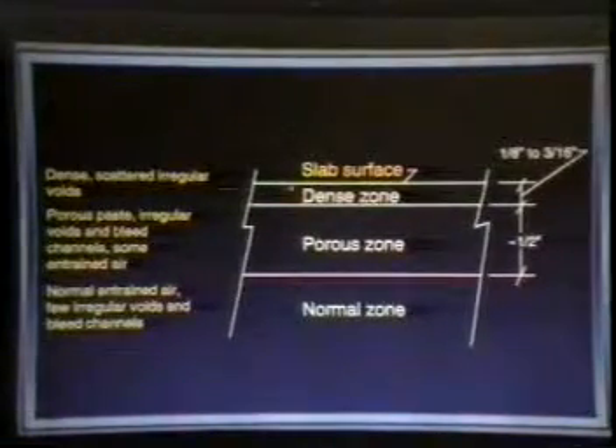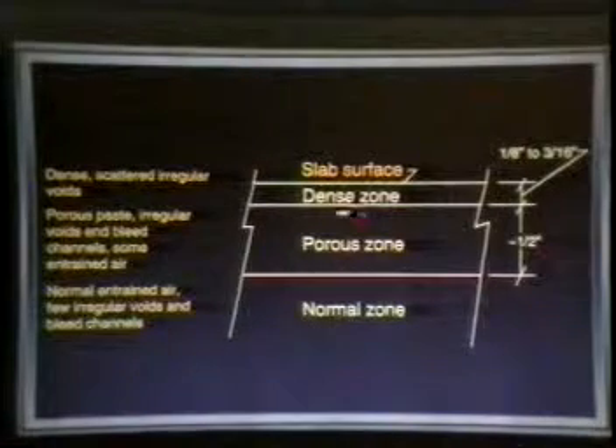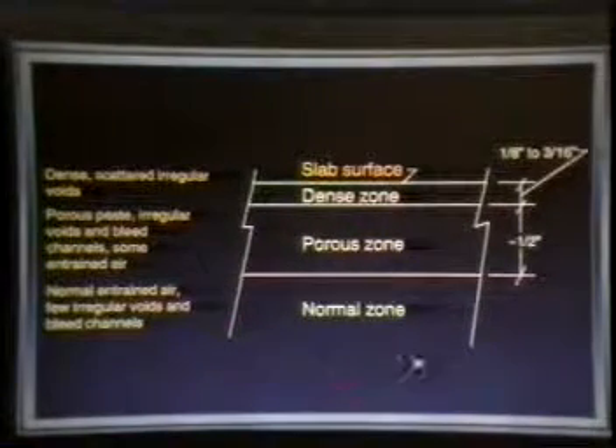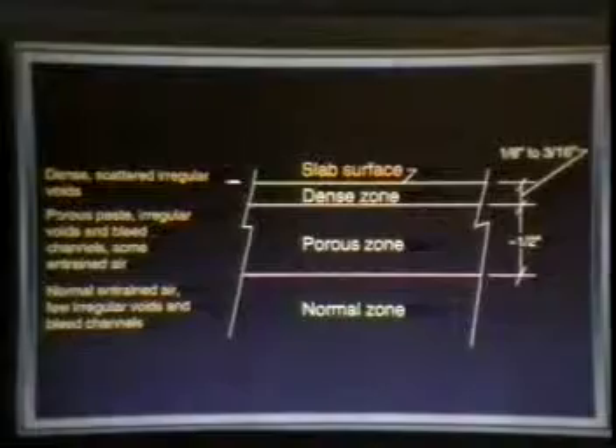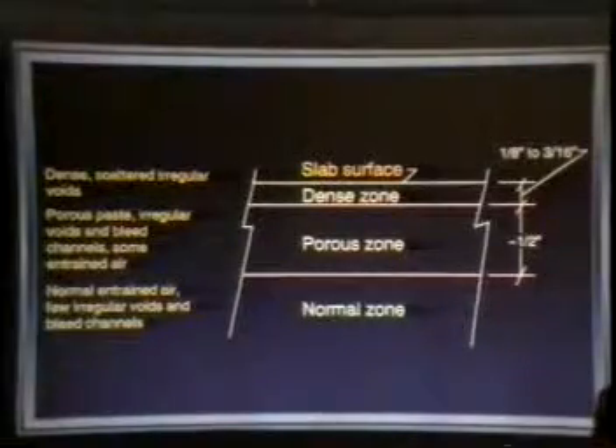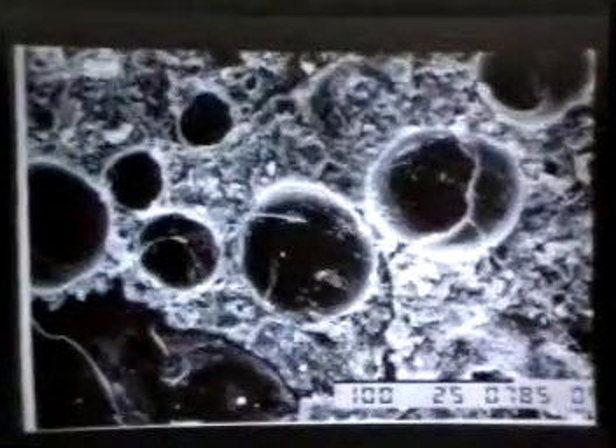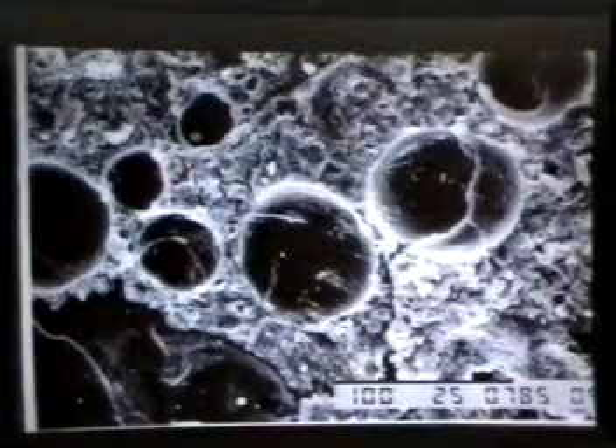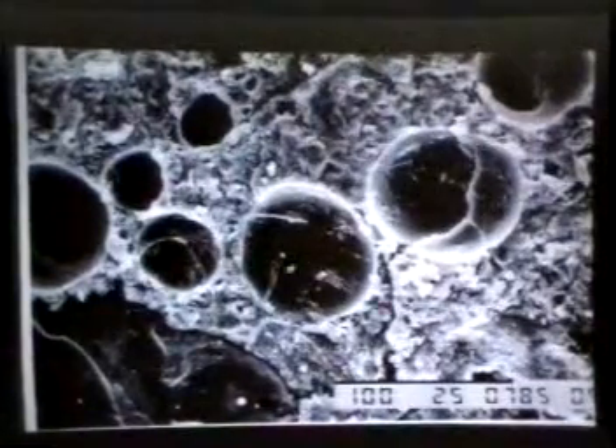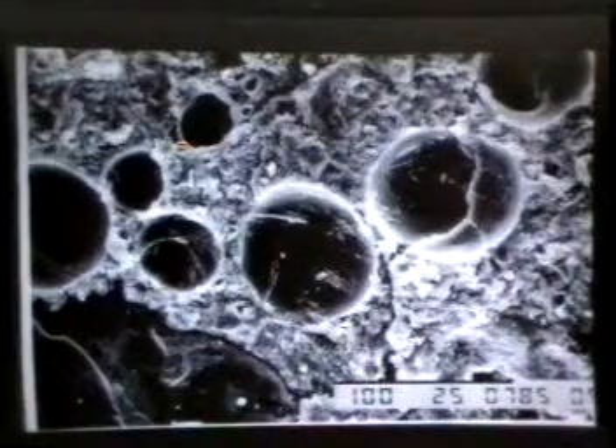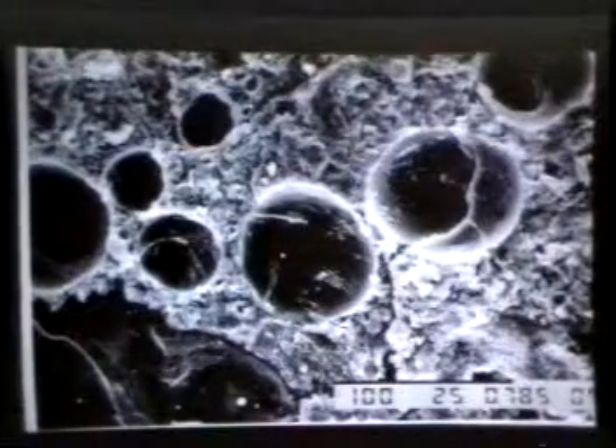If you study it carefully, you will see that you will have a dense zone, you will have a porous zone, and then you will have a normal zone. This is mainly related to some finishing problem. Air voids in concrete are very important. These are entrained air. They should be small in size, closely spaced, and uniformly distributed, as what we see here. This is what it would look like under the scanning electron microscope. They're all less than 100 microns. This is a 100 micron scale, closely distributed in the paste.